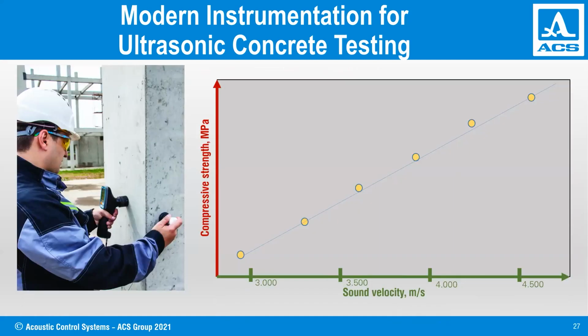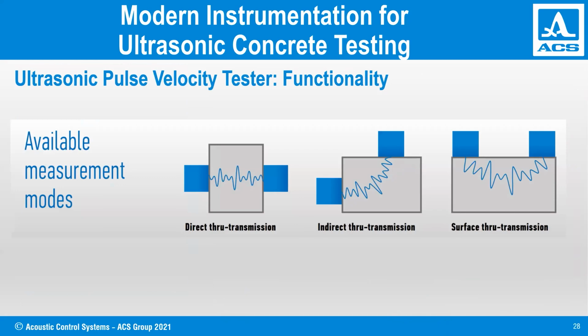Yes, there are different insonification schemes which are used. For example, we can measure direct through transmission, indirect through transmission over the corner, and then the indirect method, or it is also called surface through transmission. So the principle is simple. We just fix the distance, the so-called base, between two transducers. We measure the time, and by dividing distance by the time, we obtain the sound velocity value. And this sound velocity value is somehow corresponding to the compressive strength of the material.